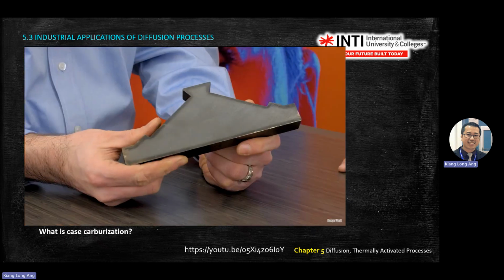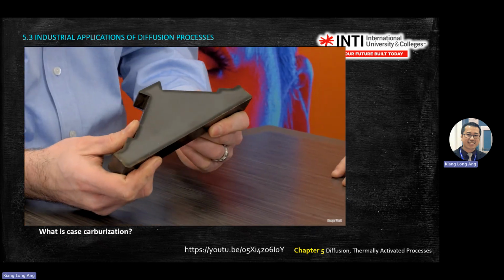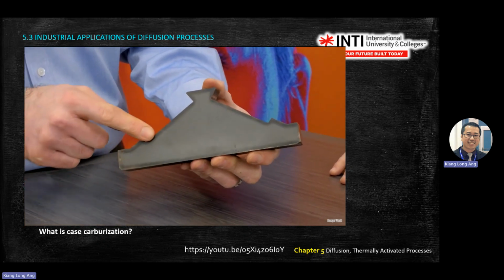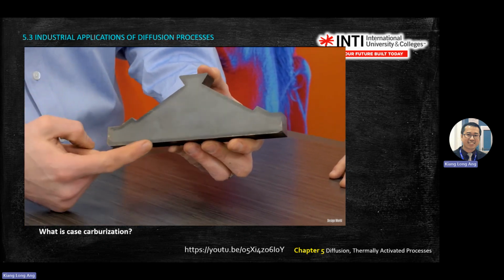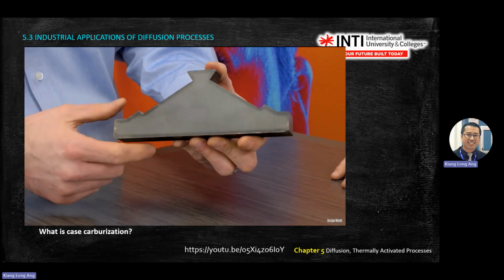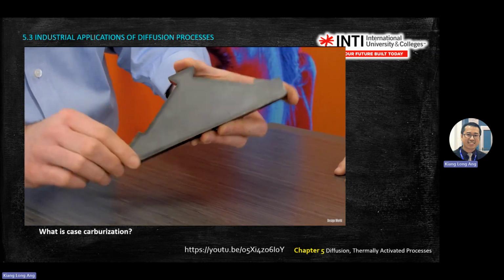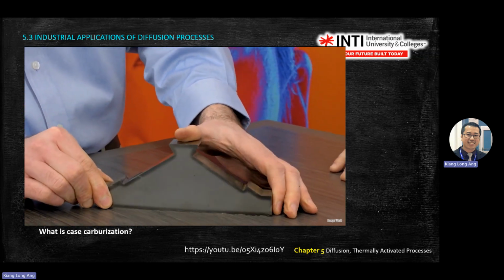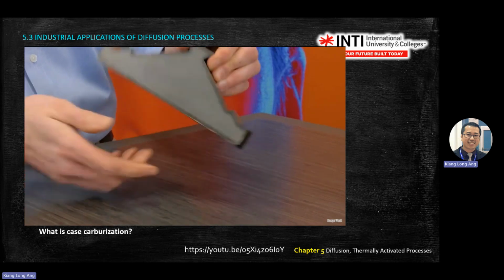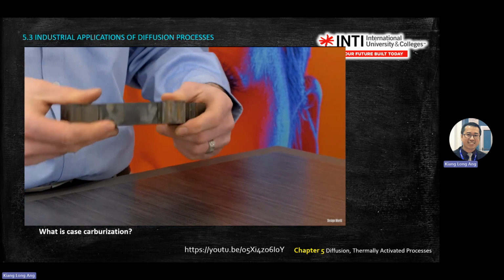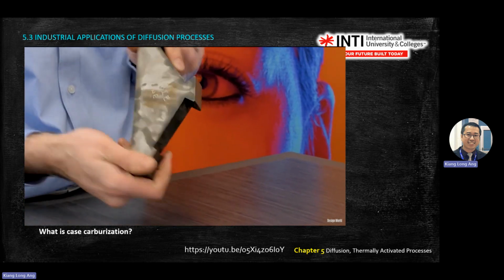Well, in relation to bearings that have case carburization, this is a through section of an inner race. As you can see here, the dark spots around the outside, those are hardness spots. And basically, this allows it to have a wear surface, but keep a ductile base material on the inside, so it'll handle shock really well. So in an application like a tapered roller bearing, where you see both axial and radial loading, it works really well. And so, John, what's the process like for case carburizing?